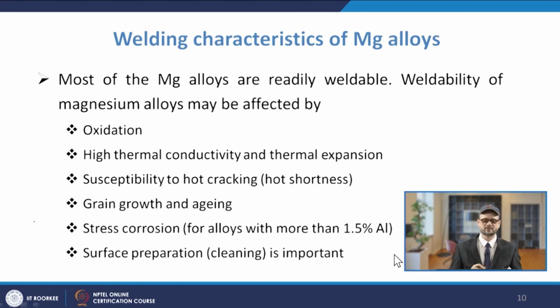Okay, most of the magnesium alloys are readily weldable. Weldability of magnesium alloys is mostly affected by oxidation, high thermal conductivity and thermal expansion, susceptibility to hot cracking, hot shortness, and grain growth and aging. Stress corrosion occurs for alloying with more than 1.5 percent of aluminum. The surface preparation is important.